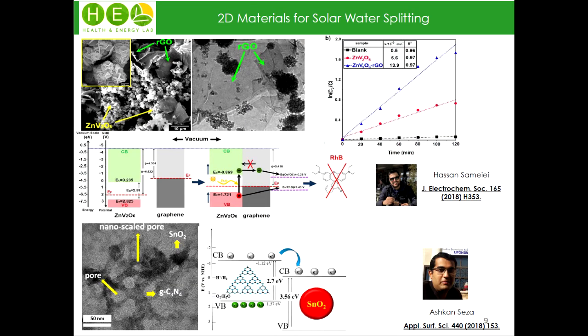Applying this material is not just beneficial for water splitting systems, but also for water treatment systems. As you know, we are suffering from dyes like rhodamine B in wastewater, and researchers try to degrade such pollution. So we applied RGO as a substrate for zinc vanadium oxide as the photoactive material, and applied the system for degradation of rhodamine B as well.